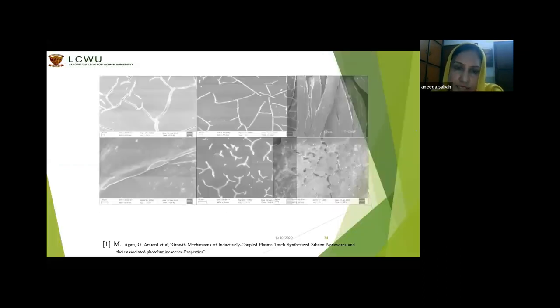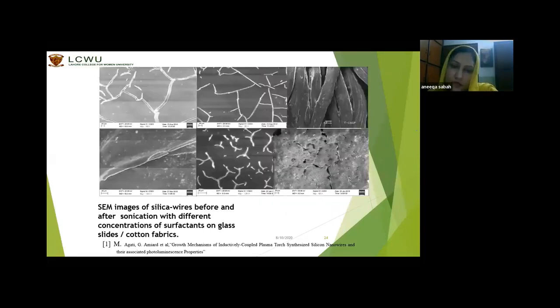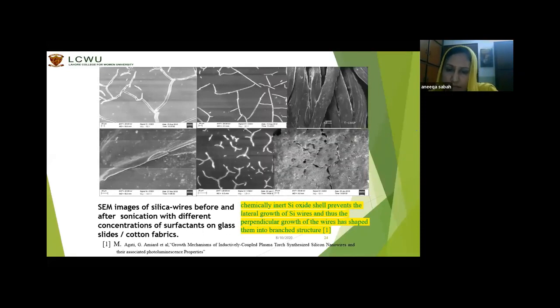Under the scanning electron microscope, we found these kinds of wires, as designed by the simple sol-gel method. Chemically inert silica oxide shell prevents the lateral growth of silica wires, and thus the perpendicular growth of wires has shaped them into a branched structure.